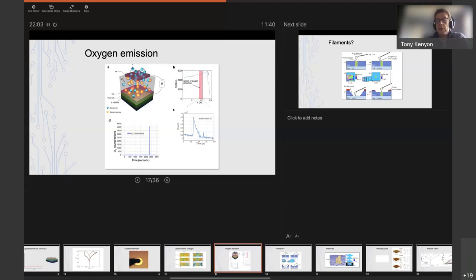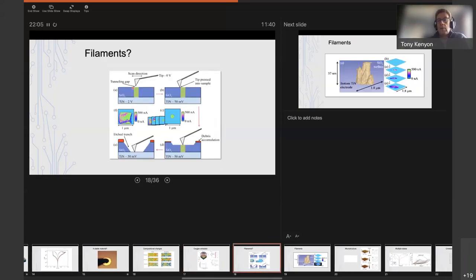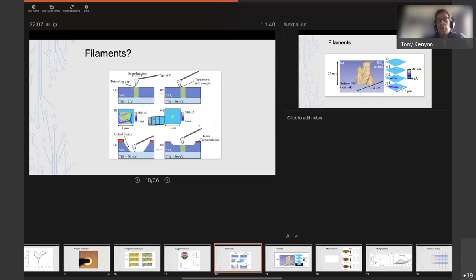So we wanted to see if we could see those filaments, and we tried looking, and the technique that we had the most success with was a technique based on atomic force microscopy. So in atomic force microscopy, you have a very sharp tip, which might be of the order, the tip radius at the end here might be of the order of maybe a few nanometers, maybe 8 to 10 nanometers or so. And that tip is attached to a long cantilever here, which we move across the surface.